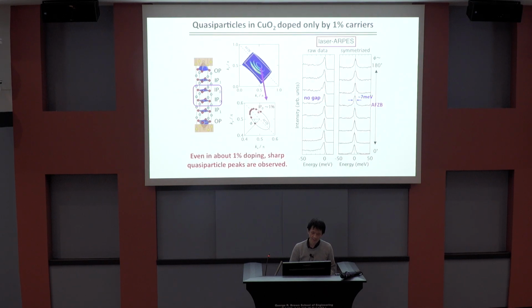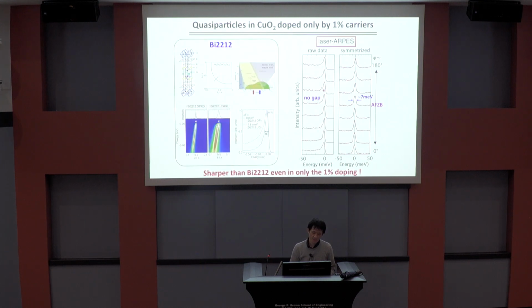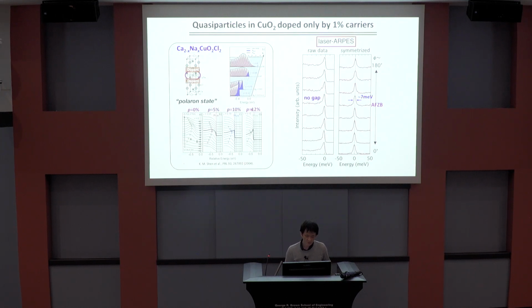So now I can say this pocket, at 1% doping, comes from these inner layers. And surprisingly, we found even this only 1% doped Mott state shows a clear, well-defined quasiparticle, much sharper than the result for the well-studied Bismuth-2212. And we didn't observe the incoherent part, which is called a polaron-like state. So the inner-protected quasiparticle layer has a very different electronic state.